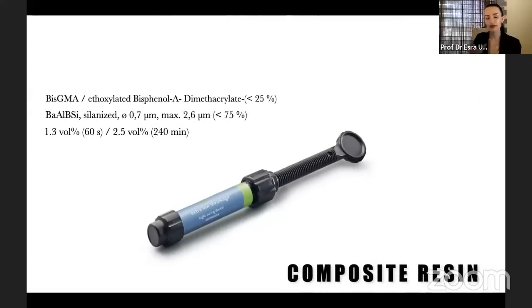We have to know also its ingredients. It includes BisGMA and also silanized inorganic fillers. As you see, its polymerization shrinkage amount is very low. This is a very good property in terms of marginal gap, marginal adaptation, marginal discoloration, and secondary caries, because if the polymerization shrinkage is high, there can be a gap between the restoration and the tooth.